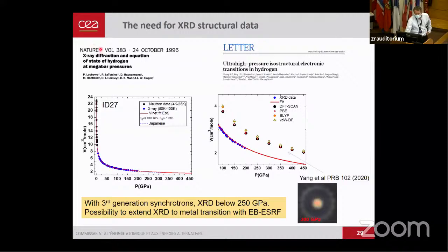As I said, I have been a user for 30 years, and in fact doing the X-ray diffraction of hydrogen was our first measurement when I came here, trying this new facility. Recently, there's been a measurement of the structure of hydrogen up to 240 GPa at the APS by the Mao group. Here we have progressed over the years to measure accurately the equation of state, and we achieved 200 GPa, but we couldn't solve the structure of phase 3.